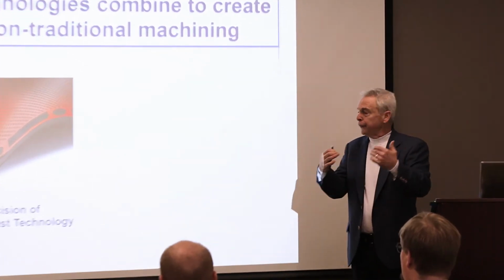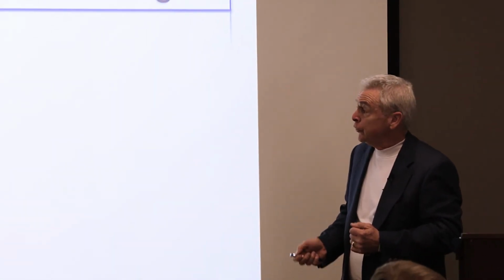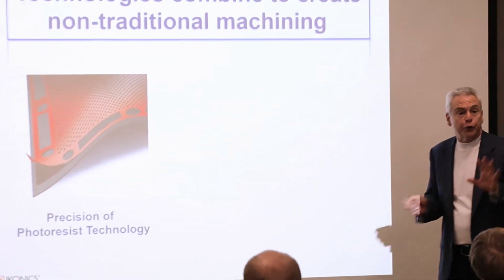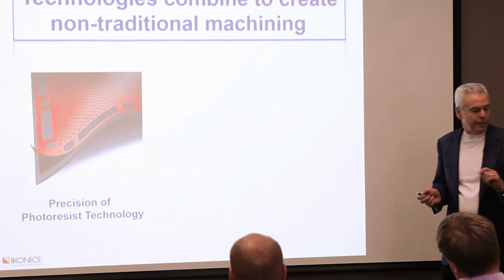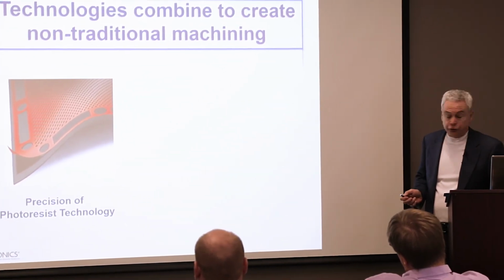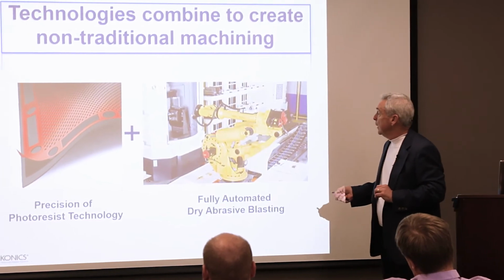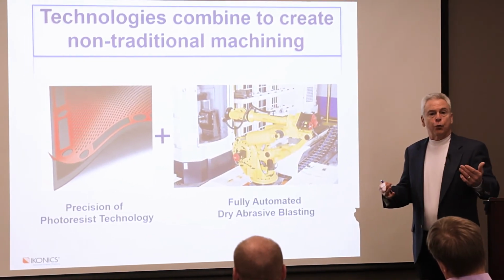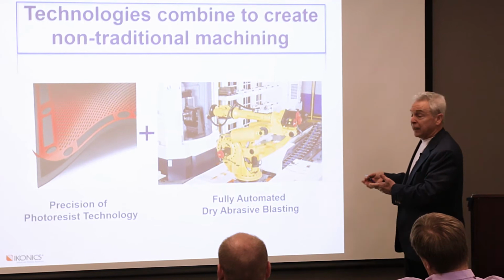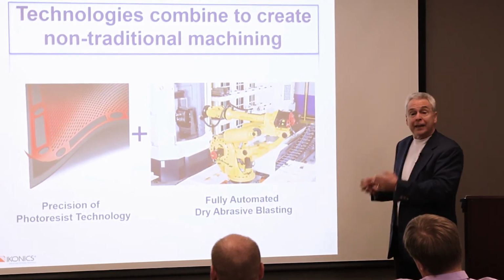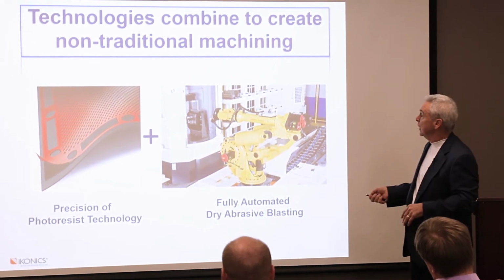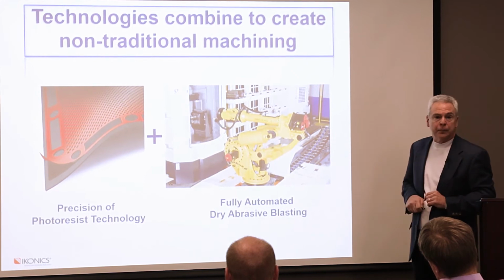Create that onto the photoresist and then apply that to the composite material, just shown here in black. So now you've got the precision of all those features in that photoresist. And then what you do is you combine that with today's advanced technology for robotics, where you can have 5, 6-axis machines that actually have sandblasting heads on them instead of drilling heads on the end.